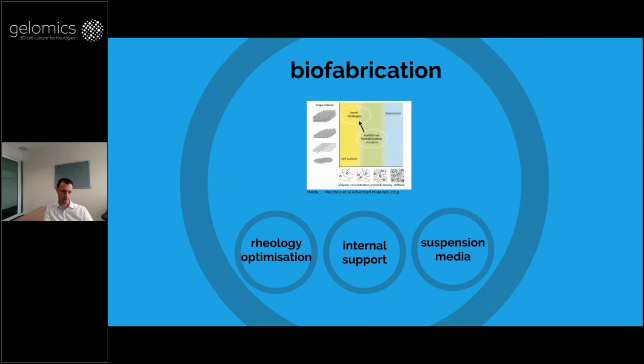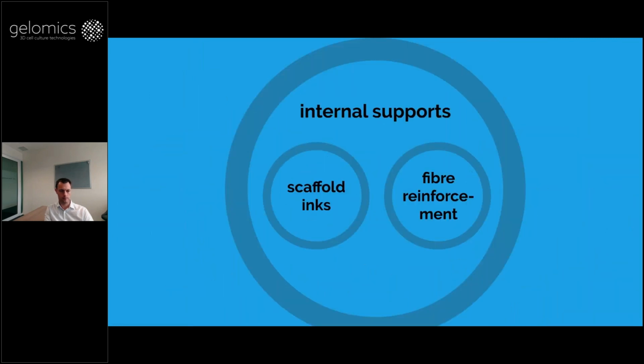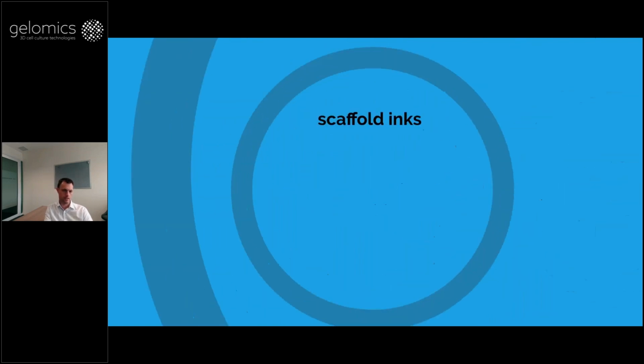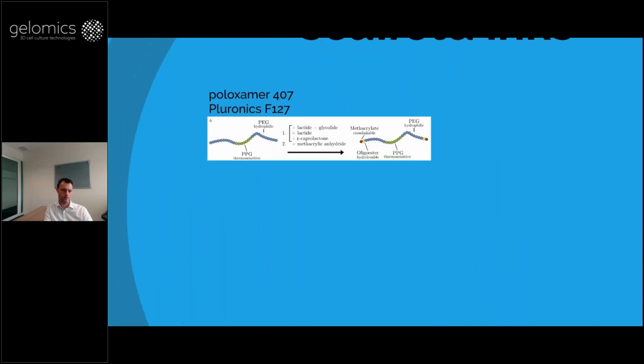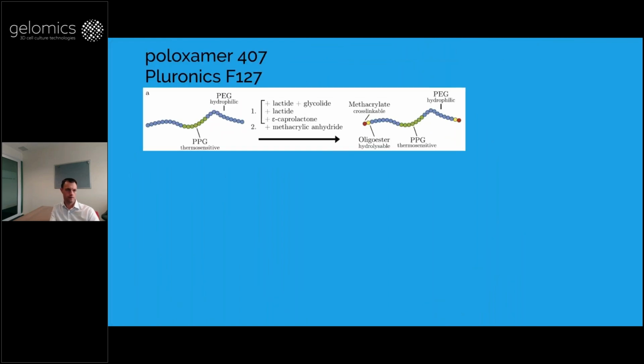Internal supports is a second strategy where you use two materials. If you have a material that supports the structure, then you can print the gel with the cells. It doesn't matter that much what its rheology is, because it will be kept in place by that reinforcing material. So we used poloxamer, a quite widely used and known material because it has really good rheology and is easily printable. We modified it with methacrylate end groups so we could cross-link it, but also with a small oligoester link, a degradable link, to make it hydrolyzable.